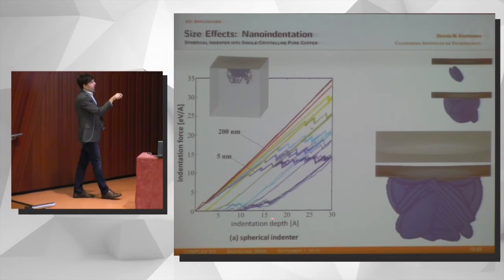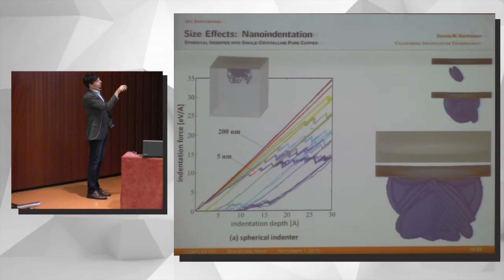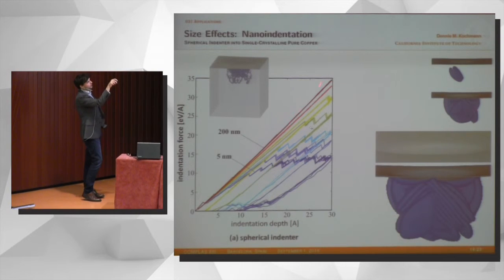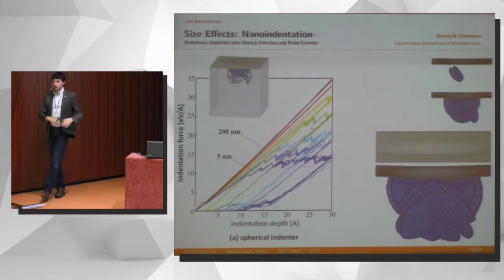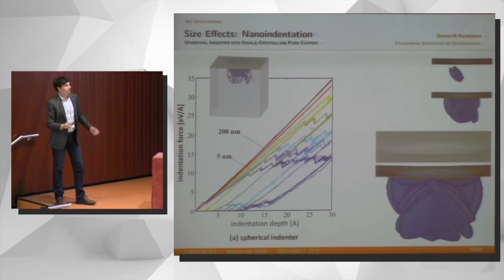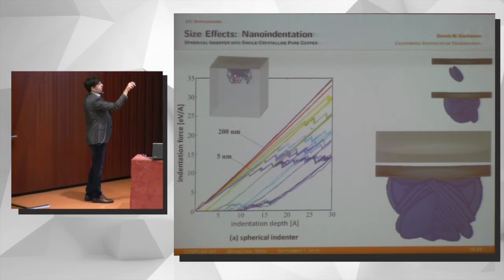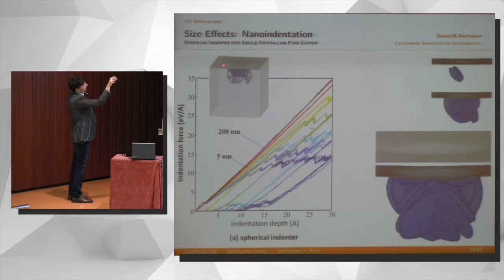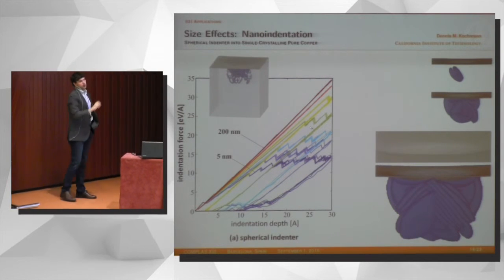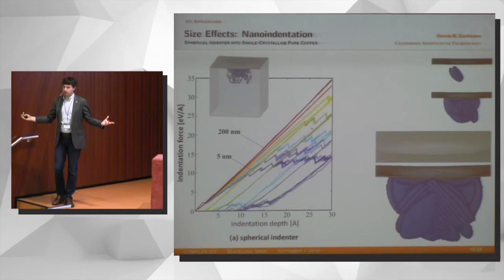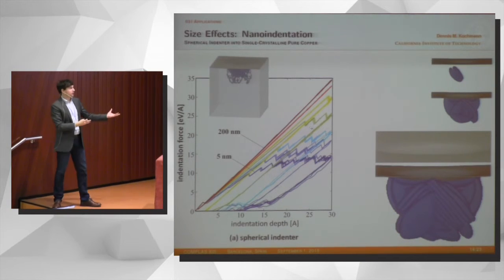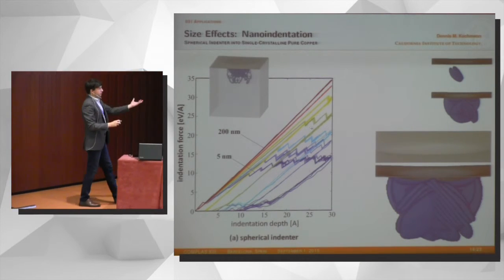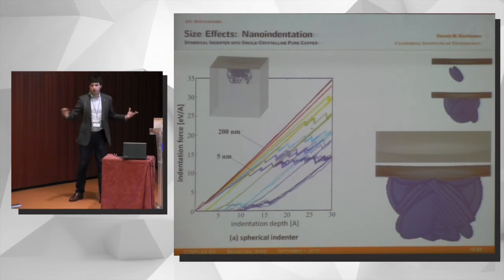This is the corresponding load versus displacement curve for a small indenter, for bigger indenters. And we can really go to sizes here which are beyond what you can normally do with MD. Indenter sizes on the order of hundreds of nanometers is only possible if we have atomistic resolution around the indent, but we keep our coarse meshed down here. That's the only way how we can go to these big sizes. Otherwise, we could never do this computationally, but it's relevant because this is the realm where experiments are.